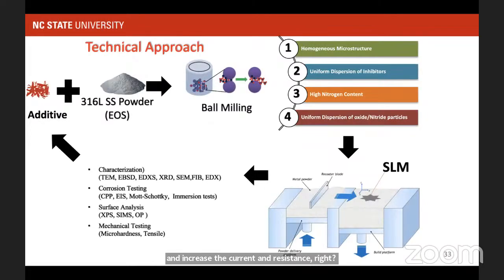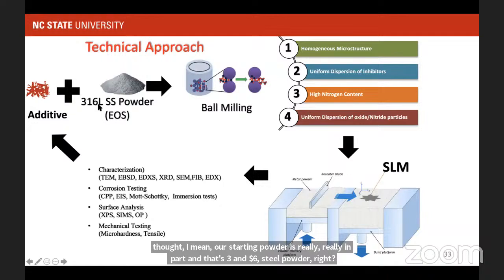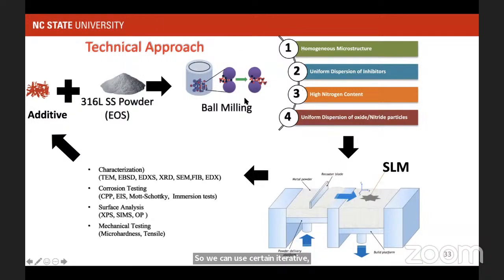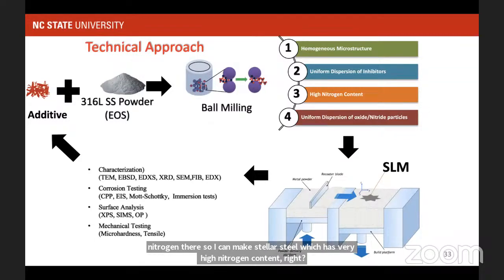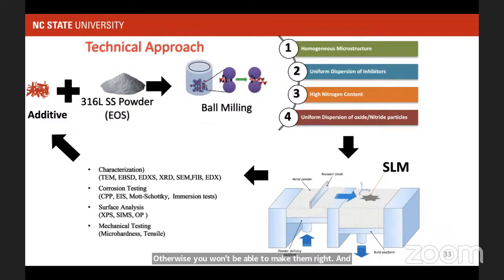Our starting powder is really important. That's 316 stainless steel powder, right? So we can use certain additives. The thought was, if I add an additive that can carry, for example, nitrogen, I can make stainless steel which has very high nitrogen content. Otherwise you won't be able to make them. People did a lot of work on high nitrogen containing stainless steels, but the challenge is the solubility of nitrogen is very limited.